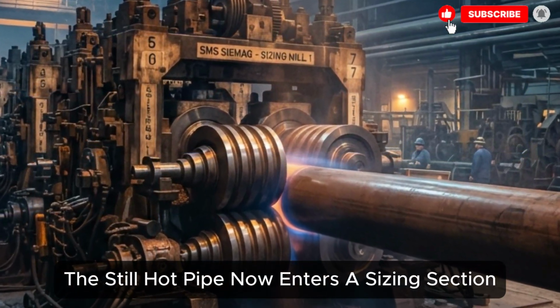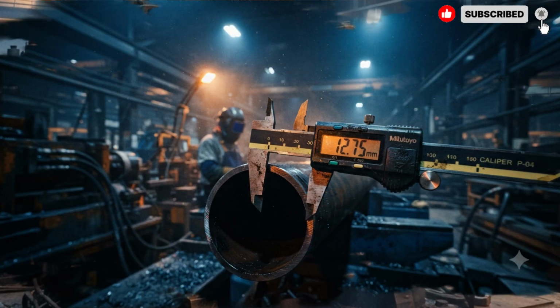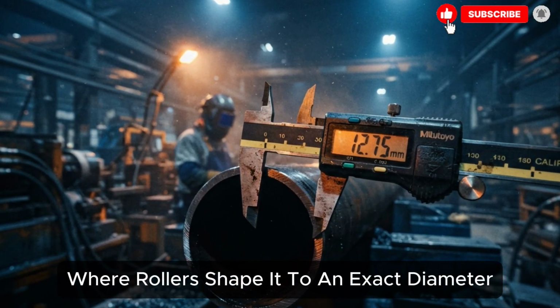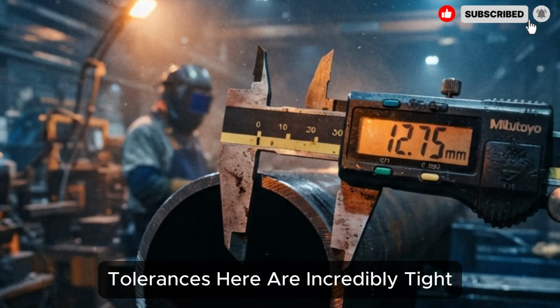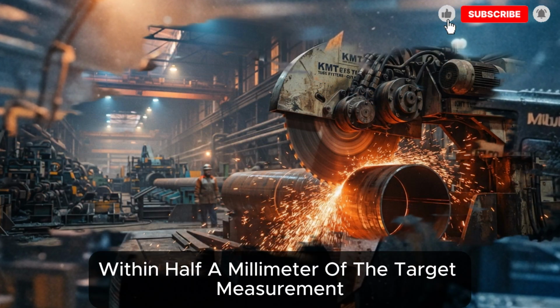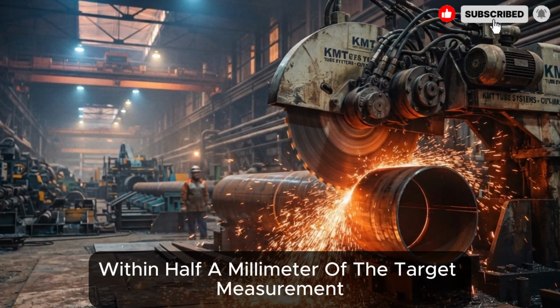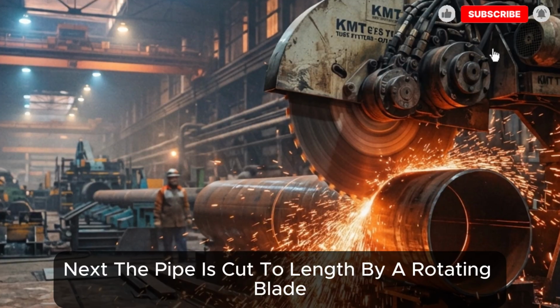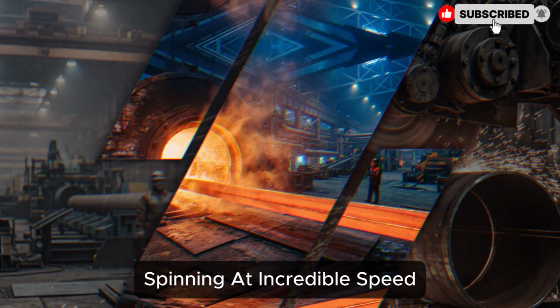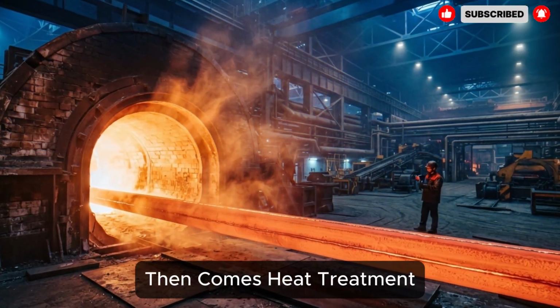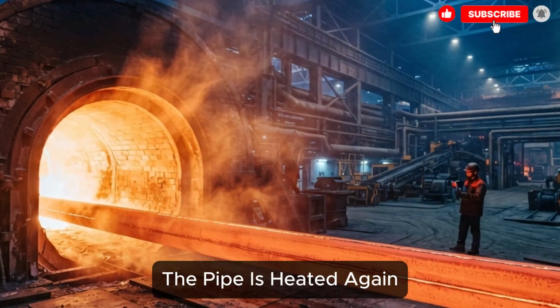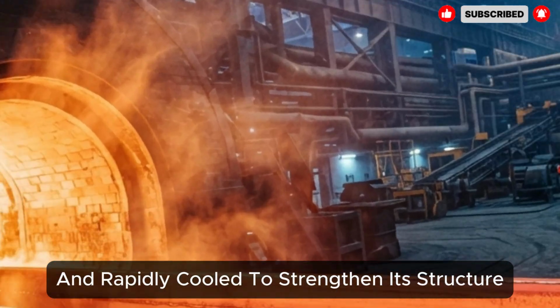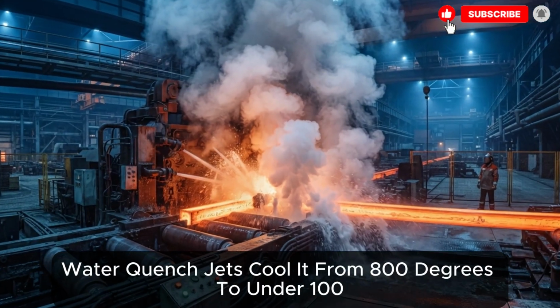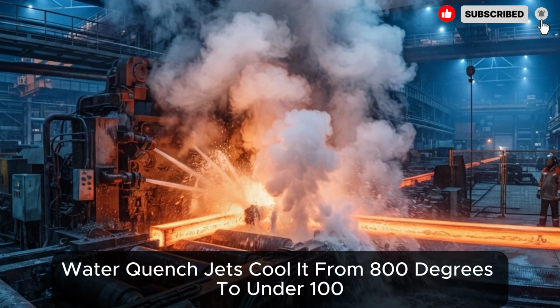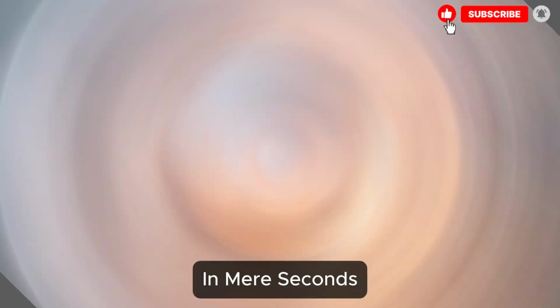The still-hot pipe now enters a sizing section, where rollers shape it to an exact diameter. Tolerances here are incredibly tight, often within half a millimeter of the target measurement. Next, the pipe is cut to length by a rotating blade, spinning at incredible speed. Then comes heat treatment. The pipe is heated again and rapidly cooled to strengthen its structure. Water-quenched jets cool it from 800 degrees to under 100 in mere seconds.